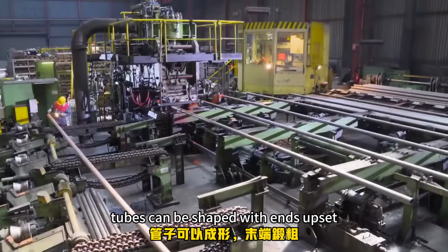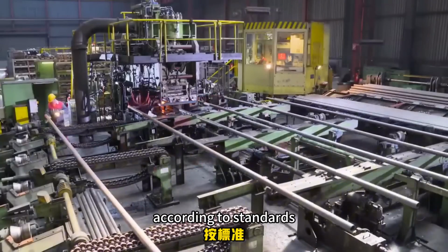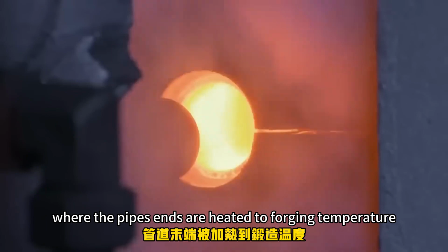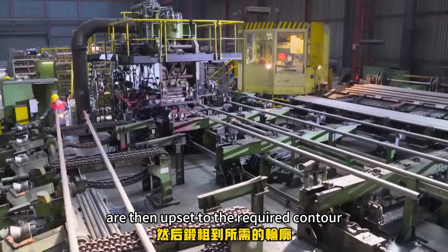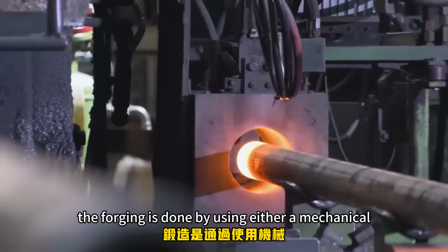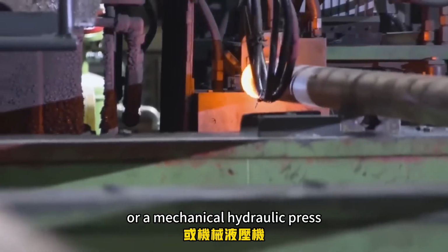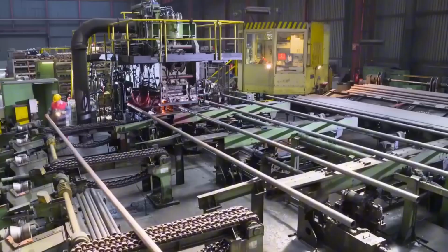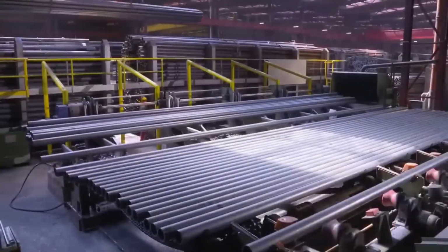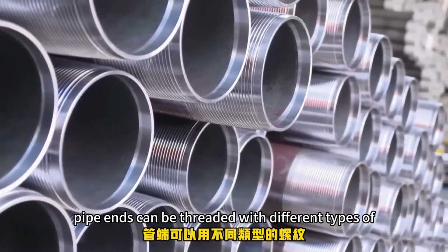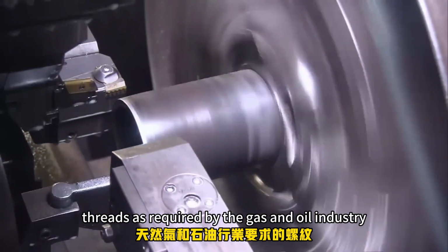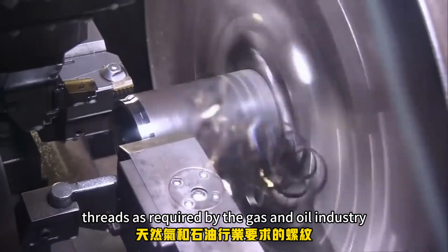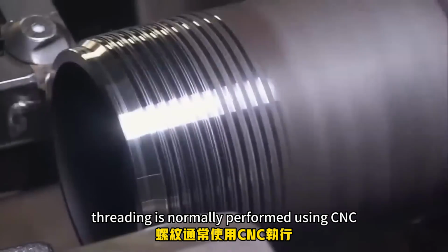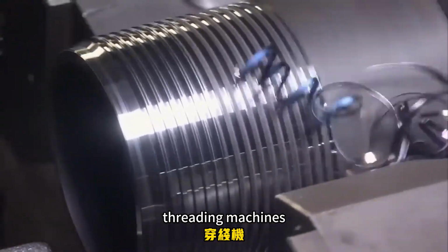When required, tubes can be shaped with ends upset according to standards, where the pipe's ends are heated to forging temperature with induction heaters and are then upset to the required contour. The forging is done by using either a mechanical or a mechanical hydraulic press. Moreover, pipes' ends can be threaded with different types of threads as required by the gas and oil industry. Threading is normally performed using CNC threading machines.